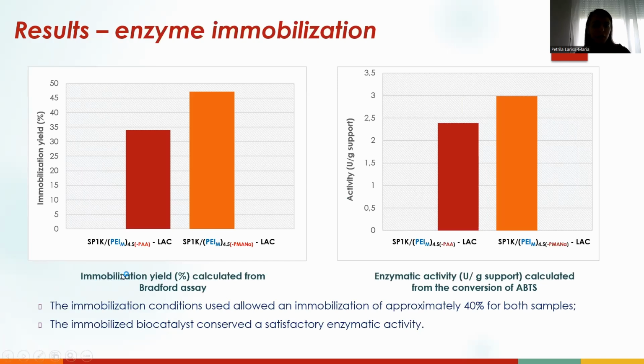The immobilization yield for laccase reached approximately 35% when using as support the composite material fabricated with polyacrylic acid, and about 45% when using the composite material fabricated with polysodium methacrylate. The difference between the two materials is related to the higher hydrophobicity of the composite fabricated with polysodium methacrylate. When immobilizing enzymes by adsorption, it is expected that the main forces that lead to enzyme immobilization are electrostatic interactions. In the case of the composite material fabricated with polyacrylic acid, it is expected that this is the main phenomenon that occurs. On the other hand, when using the composite with polysodium methacrylate, it is expected that besides the electrostatic interactions, hydrophobic interactions will also play an important role in enzyme immobilization.